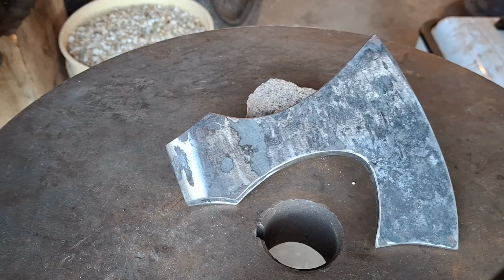And then you immediately throw it into temper between 375 degrees Fahrenheit to 400 degrees Fahrenheit. And you can let it soak for 1 to 2 hours, let it air cool or cool it under tap water, and you repeat it again. And you inspect your temper colors, and anything from a light straw to a dark bronze is okay. And if you do that, it usually results in a hardness of 58.5 to 59.5 on your RC scale, which is just perfect for axes.